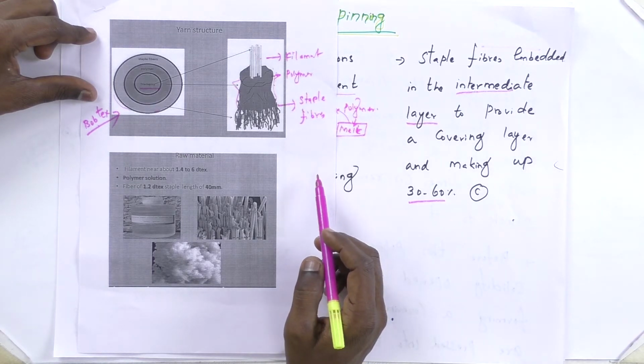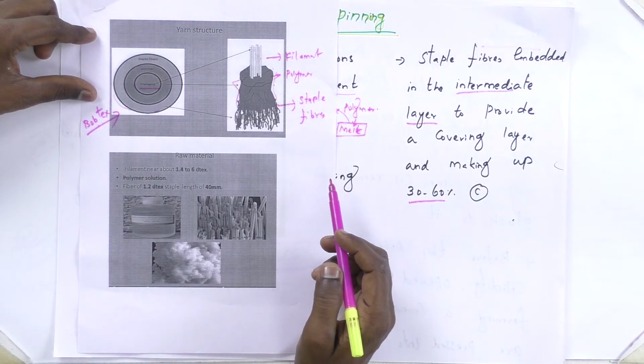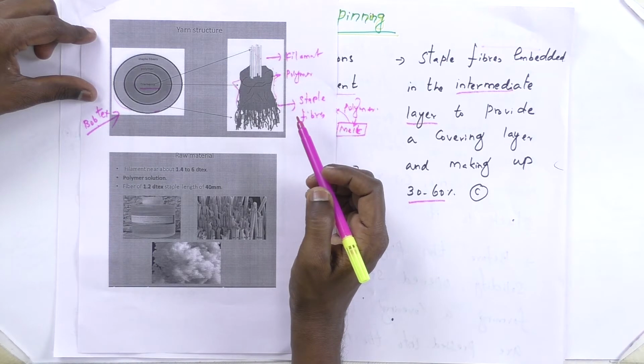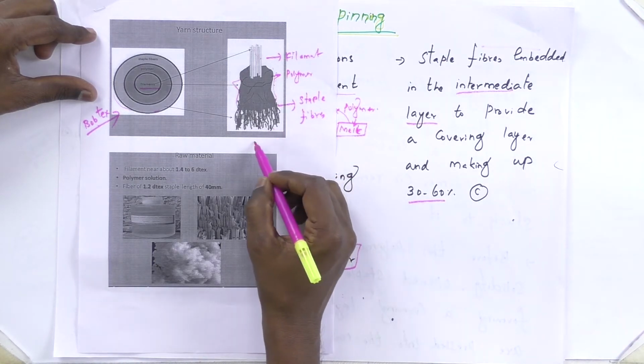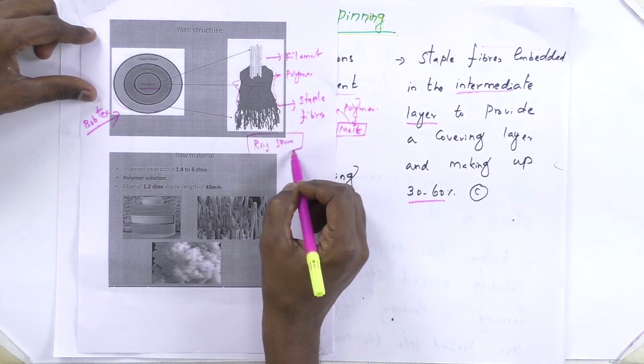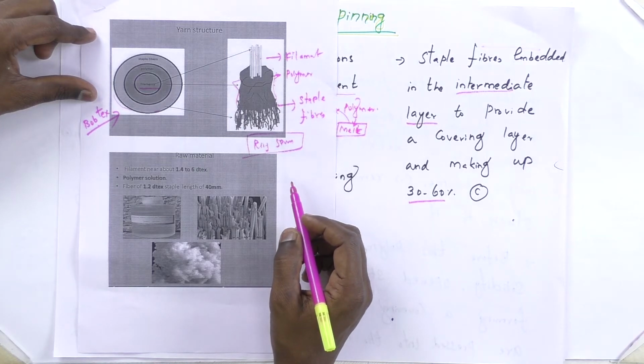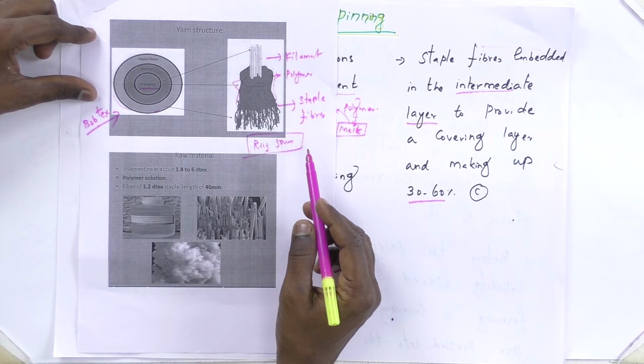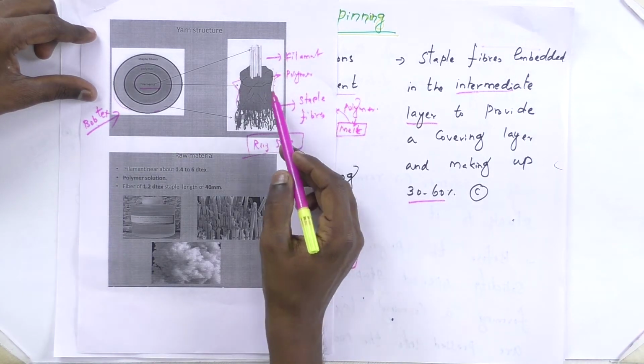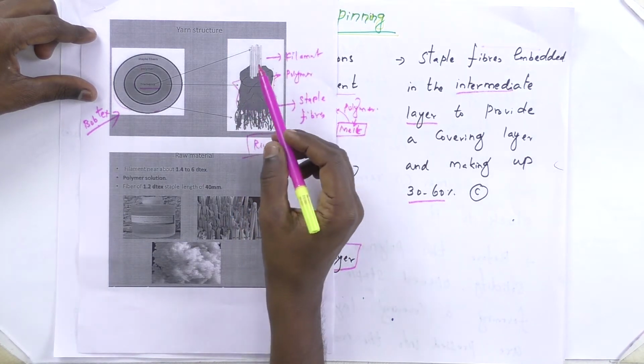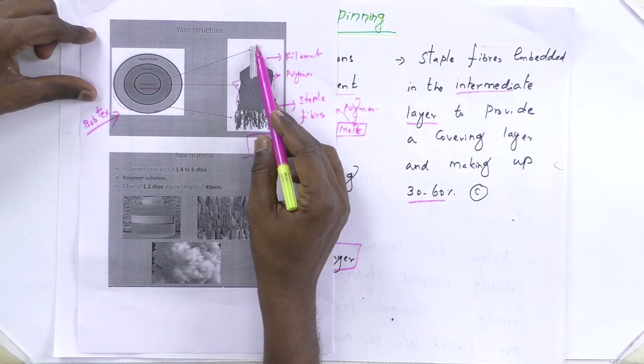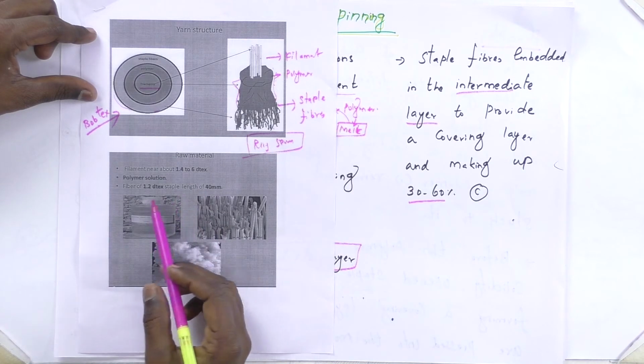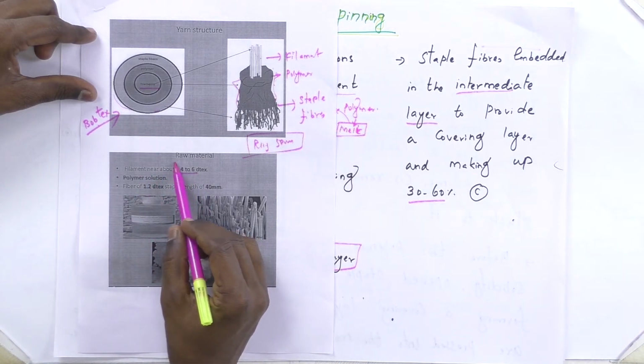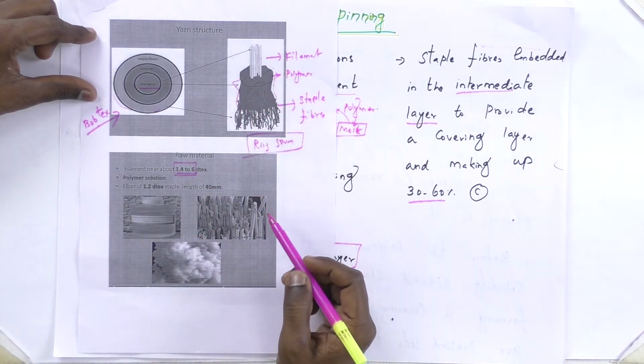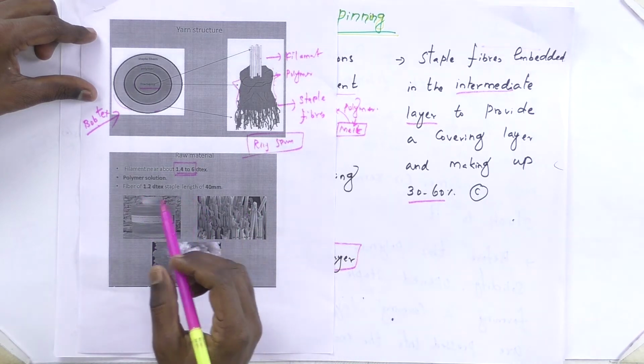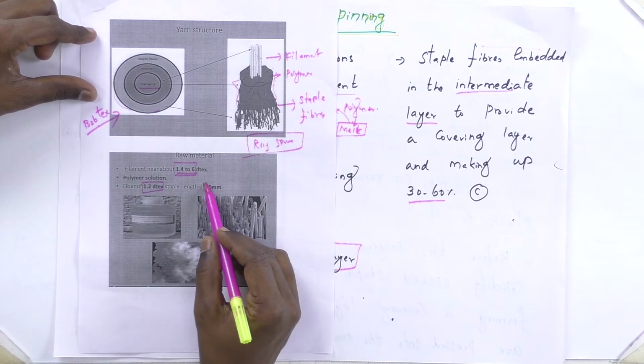So the surface of the Bobtex yarn consists of staple fibers. So it has a bulky structure when compared to normal yarn. For example, in the ring spun yarn, the surface consists of fibers. Protruding fibers may be there, but in the Bobtex spinning system, the entire surface is covered with staple fibers, which are attached with the polymer solution. The polymer solution makes a cover of the filament, which is the center core of the Bobtex spinning yarn. So for raw material, a 1.4 to 6 decitex filament yarn is used for the core. The polymer solution is also used, and fiber of 1.2 decitex up to 40 mm length is used.